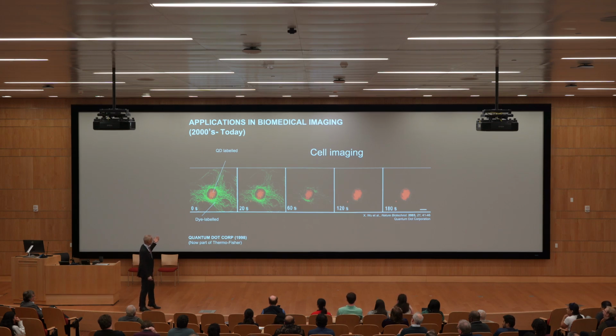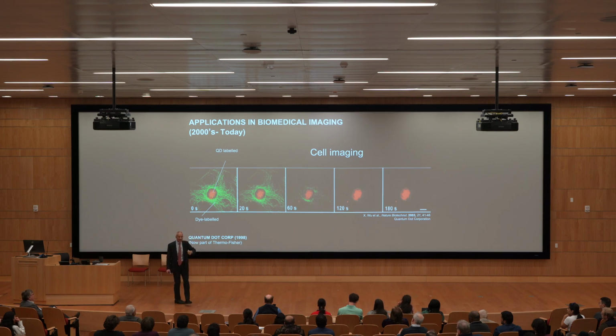This is an example from one of the papers from the company. The red nucleus of this cell is tagged with quantum dots. The green is tagged with the dye molecule, and you can see then the photobleaching of the dye. The green disappears because the dye is photobleaching, but the red stays intact because the dots are much more stable. That really showed the stability of the dots as a three-dimensional inorganic material.